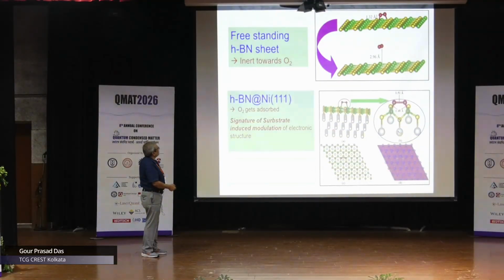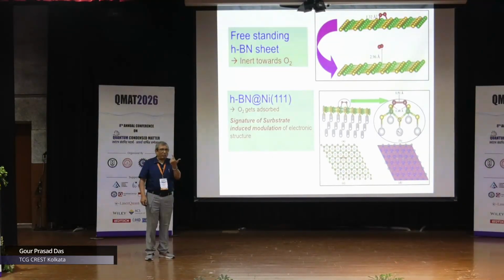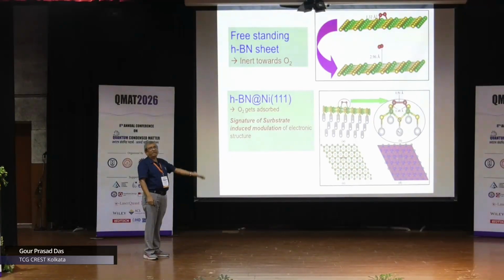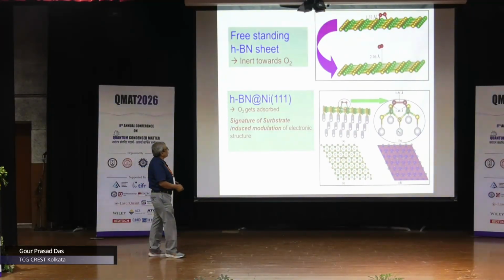It does not stay, the oxygen does not like the freestanding HBN. But lo and behold, when we put the same hexagonal boron nitride on a nickel 111 substrate, incidentally, nickel 111 and HBN have the same lattice matching. So when you put that and then you try to bring the oxygen, it remains. Why? What's the reason? Freestanding, it goes away. Whenever you put it on nickel 111, oxygen gets adsorbed. So there must be some substrate-induced modulation of electronic structure. Not only that, there is something even more.